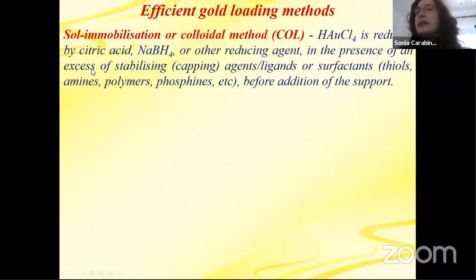And so, as I said before, impregnation is not active. It's not good to produce active gold catalysts. So let's see some efficient gold loading methods. So, especially for carbon materials, carbon supports, gold can be loaded by sol immobilization or a colloidal method, in which the gold precursor is reduced by citric acid, sodium borohydride, or other reducing agents in the presence of an excess of stabilizing agents or surfactants before adding the support. So these surfactants keep the gold nanoparticles apart from each other, and they prevent them from agglomerating, which is a problem, of course.